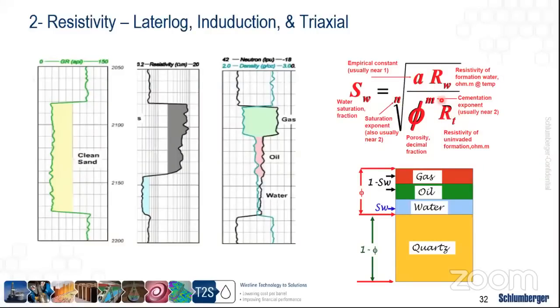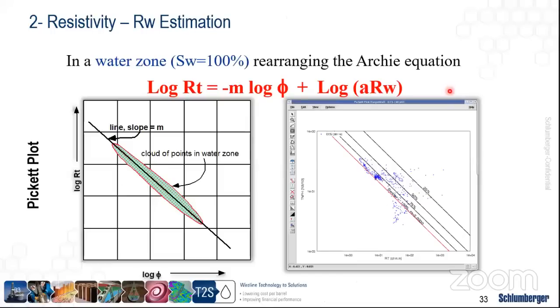So by doing this, we can start to estimate and compute how much water saturation we have. And using the SW, we can subtract 1 minus SW in order to get what's remaining, which should be contributing to the hydrocarbon, whether it's oil or gas. But the question is, how do we get RW? So RW, typically, we can get it from different methods, but the most common method, if we have a water zone,